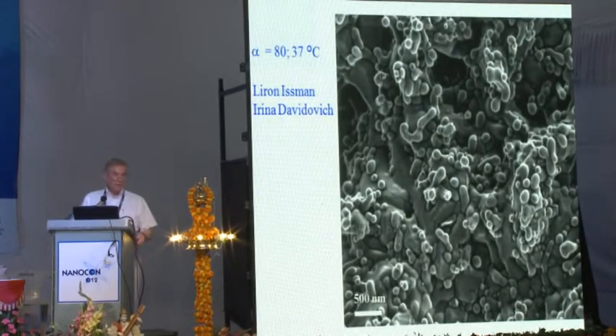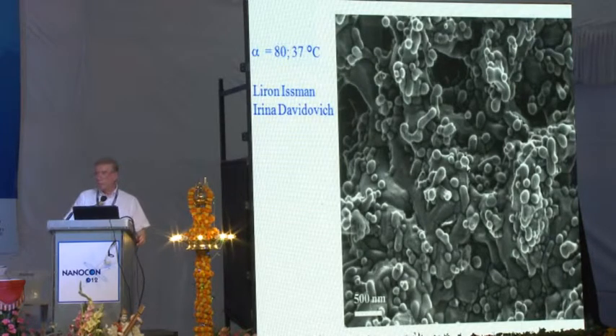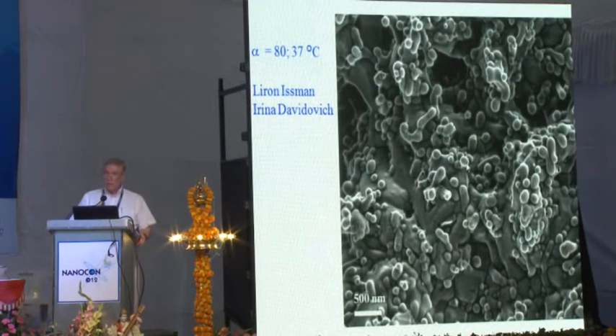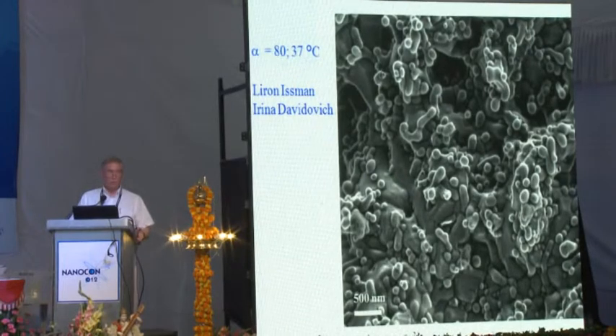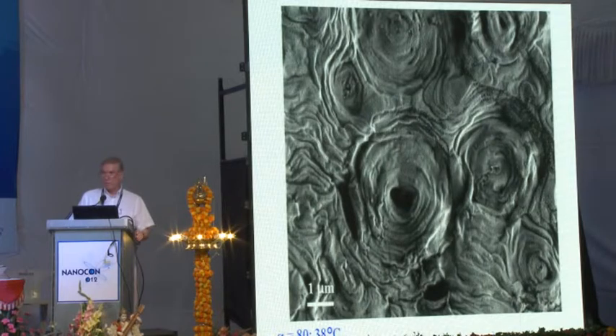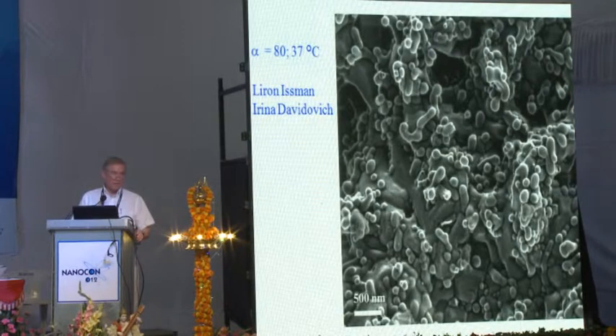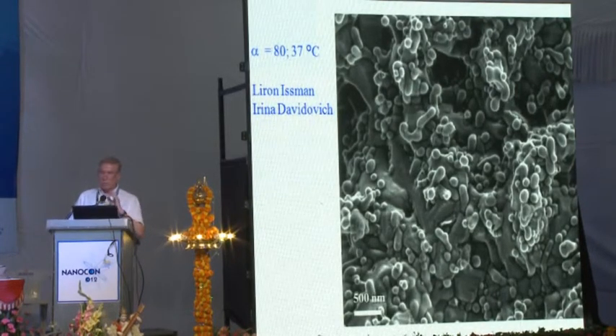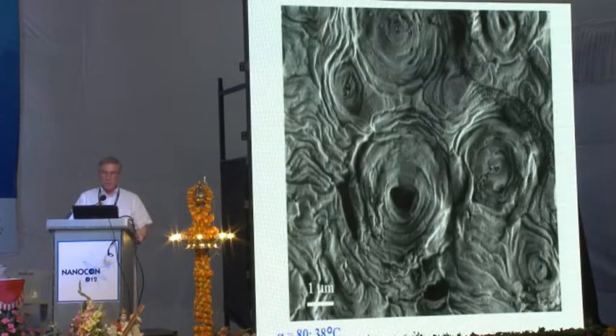Alpha 80, that is, we have 80% oil in the oil-water mixture. And what you can see very well here are very small domains. Those little blobs are small domains of water in the oil. If you are not careful and your temperature goes 1 degree off, you get a very different structure. It phase separates and you get a lamellar structure. So you see this is 38, this is 37. So very good control of your temperature, which is afforded by the controlled environment vitrification system, is really essential.